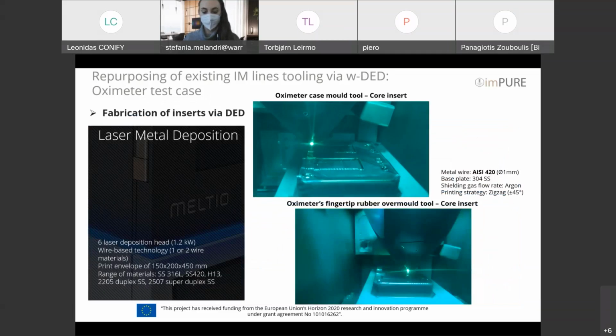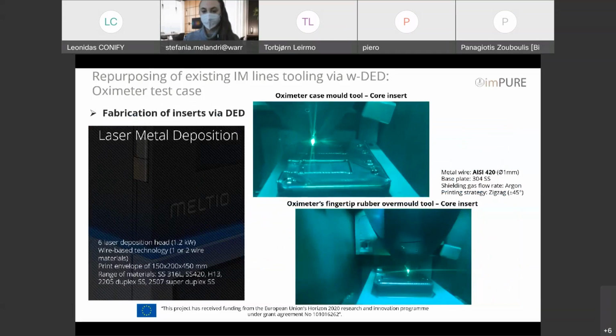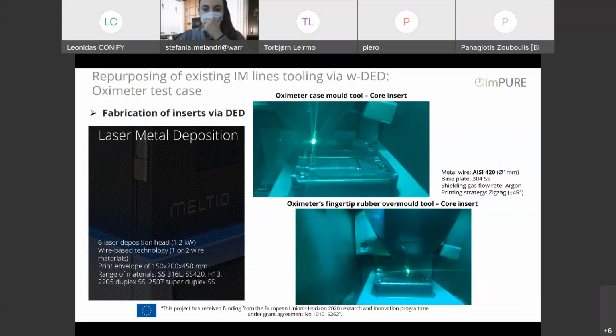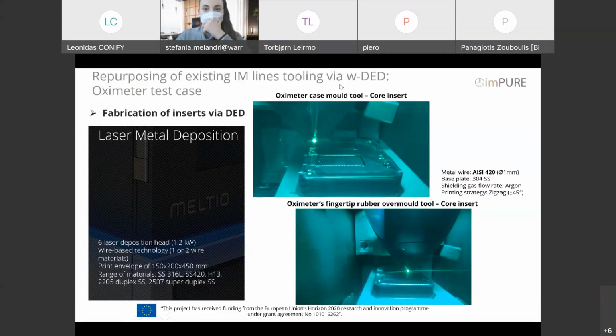However, we used our wire DED system to produce the oximeter case molds with a lot of success. We used a mild steel substrate. We had argon as an inert gas in our build chamber, and we used a zigzag scanning strategy to deposit the material in order to avoid warping or cracking or any other defects that could cause failure of our build. So both mold tools were built successfully. If we can go to the next slide, please, Stefania.